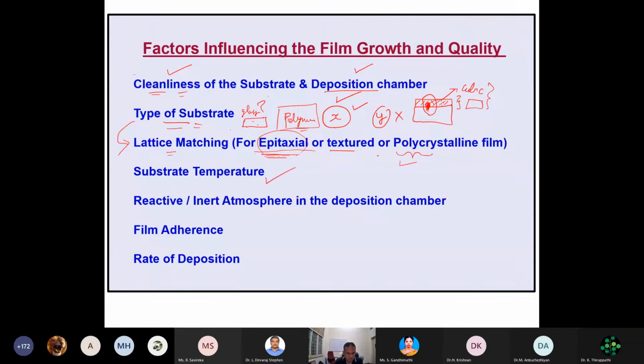So substrate temperature is also important, as I told you, for glass or polymer. Then what kind of atmosphere you are going to give? That is also very, very important. I can use an inert atmosphere by putting in helium gas, or sometimes krypton gas, or I can use oxygen also. Depending upon what your material is, I have to choose this particular atmosphere, because this will help me to have a reaction during formation of the film, or it will help me to modify the kinetic energy of the evaporated species to control the rate of deposition of film growth.